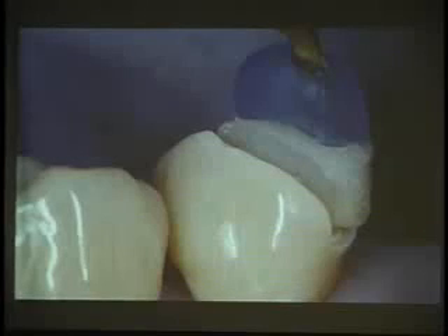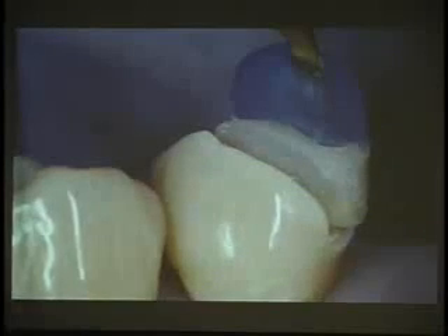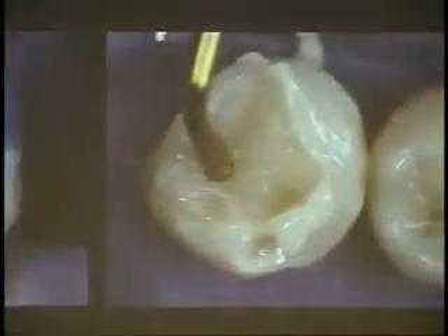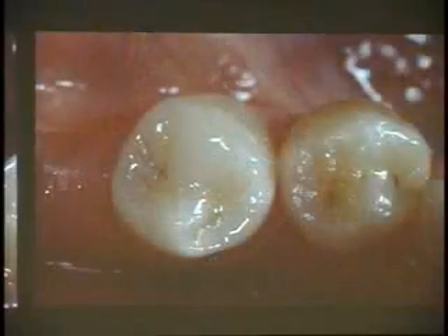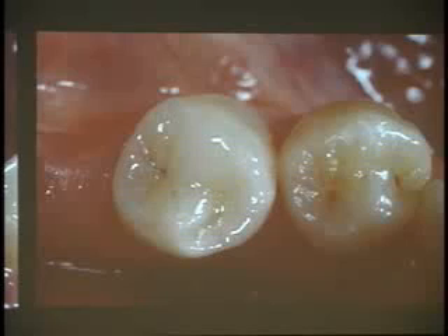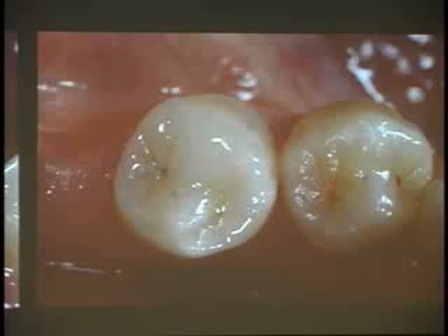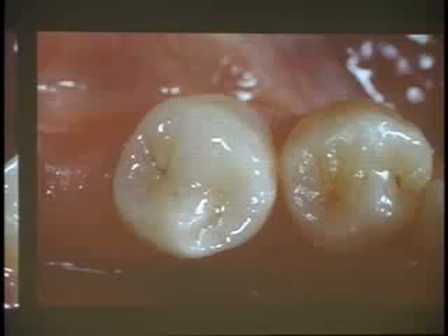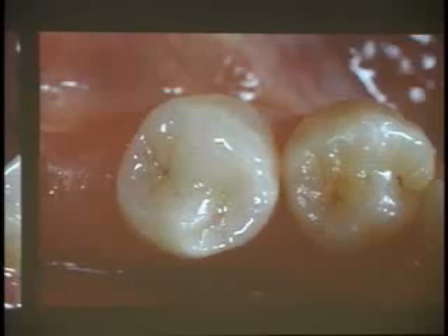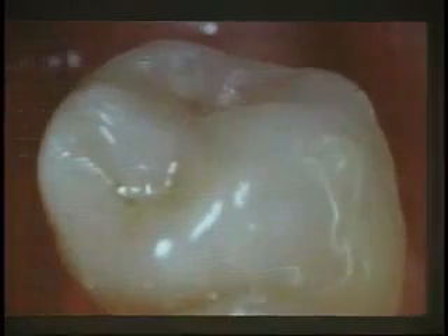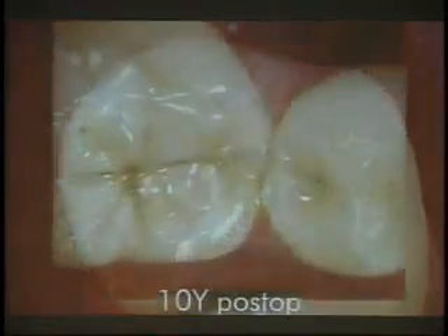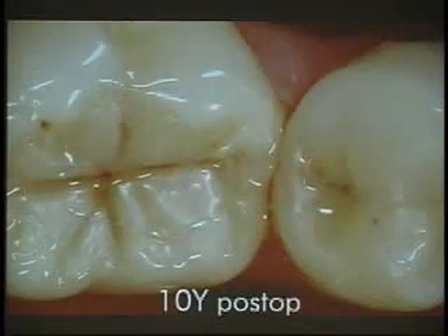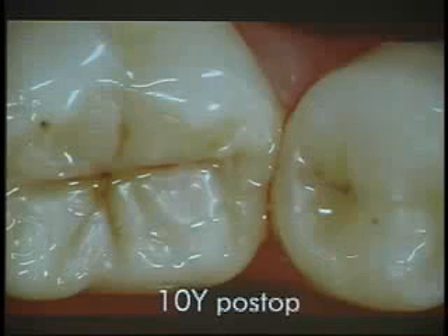At that time I was already using a light-cure restorative composite as a luting agent for this restoration, etching the marginal enamel, of course, and also roughening the internal surface of the restoration to get a bond to this composite. And that was immediately after placement. And this is now, I apologize for the bad quality of the picture, 10 years later.